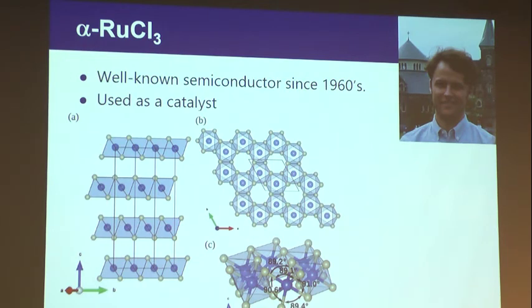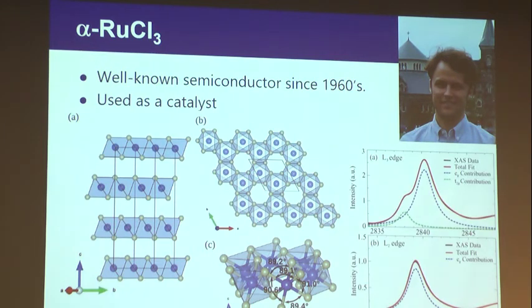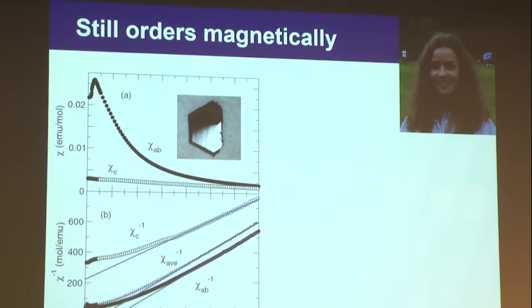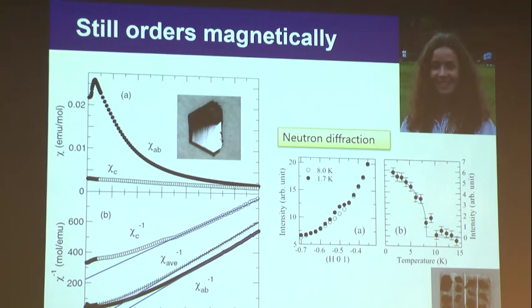So I asked my talented graduate student, Ken Plumb, to synthesize this, and we did an X-ray absorption experiment. And indeed, when we compare the L2 and L3 edge absorption spectra, we can show that the spin-orbit coupling is relevant in this material, and therefore Kitaev physics must be really important in this thing. Sadly, again, it's a recurring theme that it still orders magnetically. This was work done by another grad student, Jennifer Sears. When we measured the magnetic susceptibility, it showed clear magnetic order in a single crystal sample. And we can actually do neutron scattering because ruthenium doesn't have the problem that iridium has in terms of doing neutron scattering.